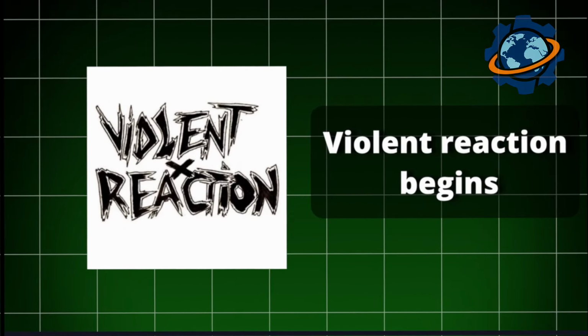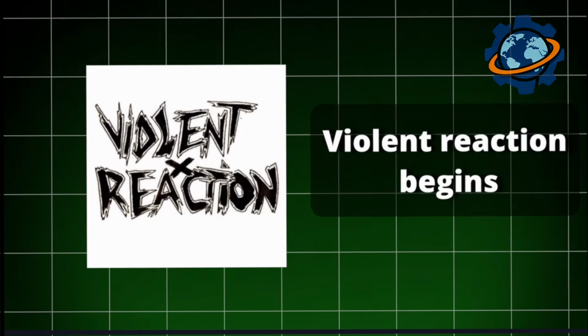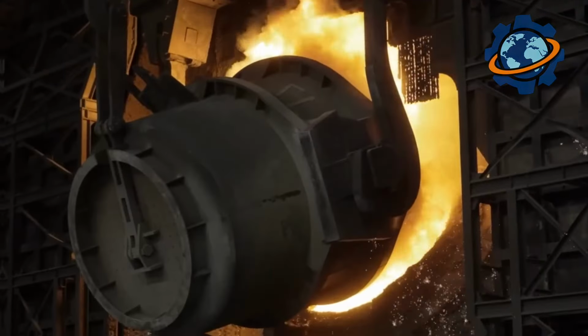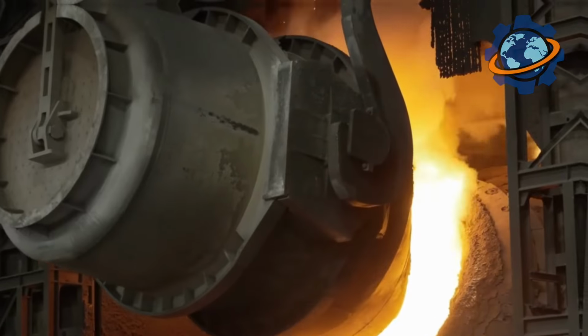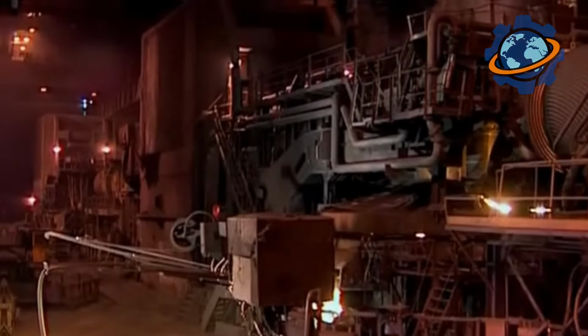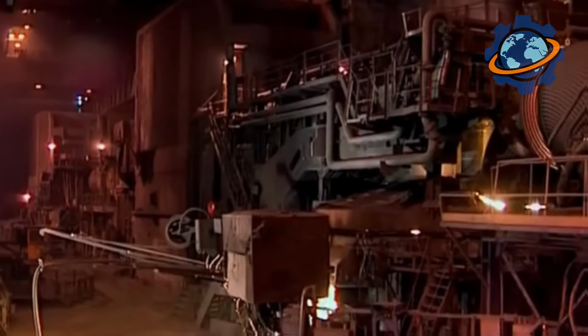Violent reaction begins. Oxygen oxidizes carbon, silicon, manganese, impurities in pig iron. These exothermic reactions release enormous heat. Temperature rockets to 3,200 degrees Fahrenheit. Metal boils and churns. Flame tongues several feet high shoot from the converter mouth. Sparks and molten drops fly everywhere.